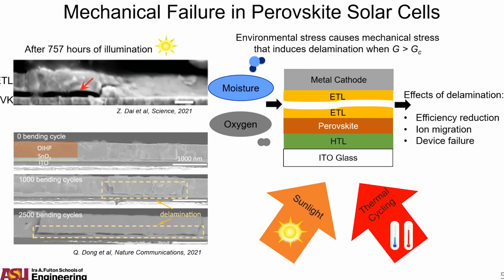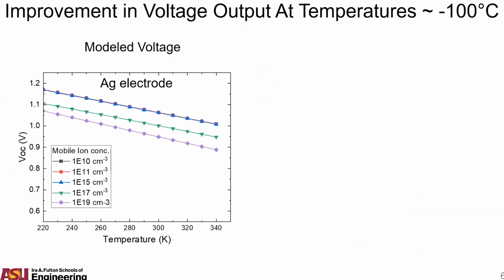So we've been working to engineer more robust perovskites mechanically through various techniques, and we've also been studying how these can perform at different temperatures. So we've started by looking at a combination of simulation and experimental work to understand how these voltage outputs and device performance would vary as a function of temperature. This is showing actually that performance tends to increase at lower temperature due to lower dark currents and less recombination.